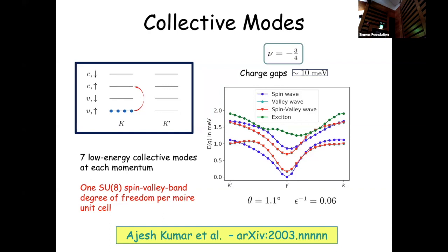And there's this branch of collective modes that exists throughout the Brillouin zone, which corresponds to basically, for the excitation spectrum, to having a local degree of freedom on every lattice site. And so it acts like it has a local electric degree of freedom on every lattice site. It's happy to be in any spin valley state and in either band, doesn't care much which band it's in. It costs very little excitation energy to make these collective modes.